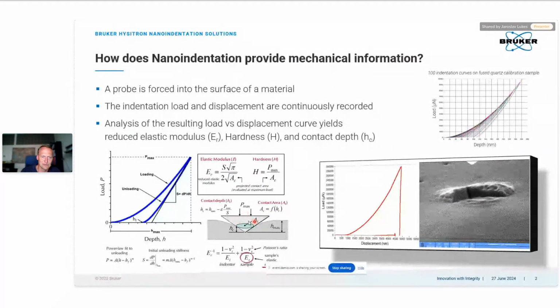So this is the most influential parameter, and basically what that also means is that the reduced modulus is given by the slope of the unloading segment, so how the material is pushing back the tip when you are unloading, and the hardness is simply the maximum force divided by the contact area. So we need to produce some deformation to the material to actually get the hardness properties right. But I'll talk about that later.